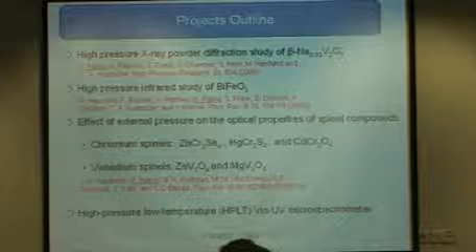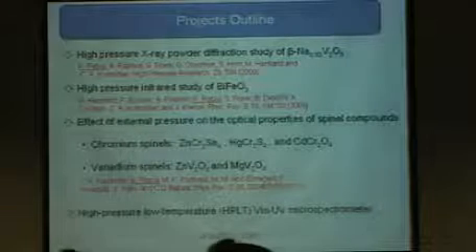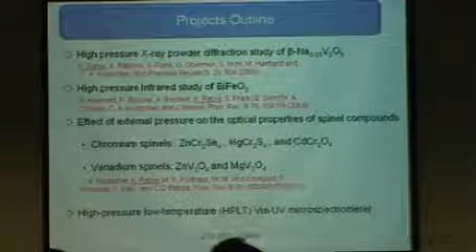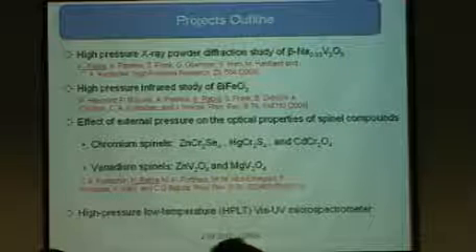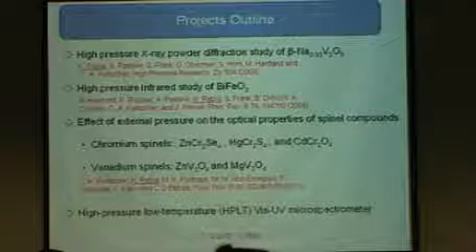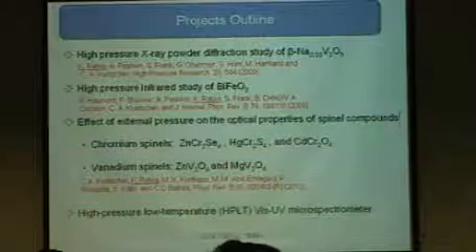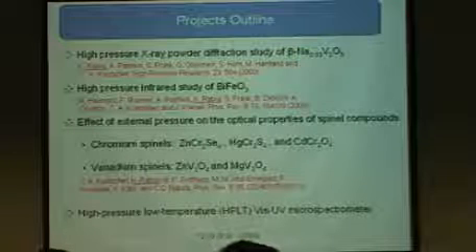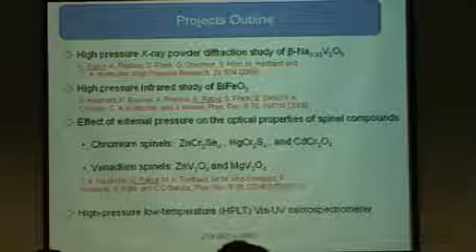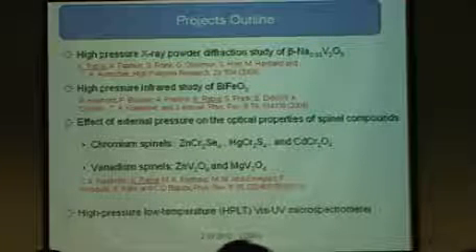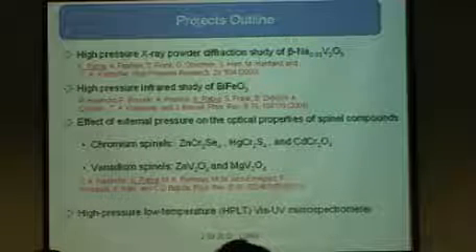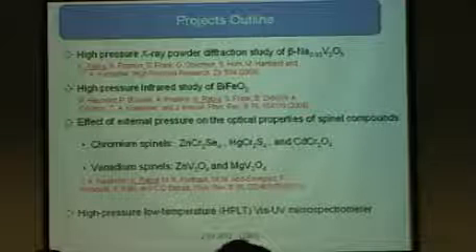Here is the outline of the projects that I did during my PhD. I was working on various transition metal compounds, and these were investigated by high-pressure infrared microspectroscopy, except one system, beta sodium vanadate, where we used X-ray powder diffraction to confirm the structural transitions, which were probed by Raman and infrared microspectroscopy under pressure. All other compounds were investigated by high-pressure infrared microspectroscopy.